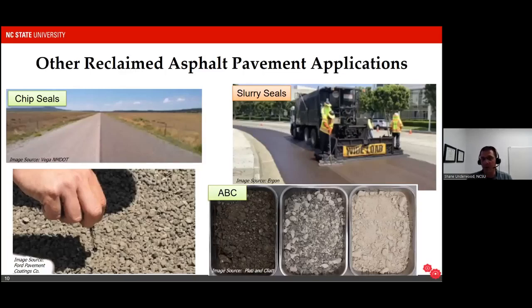But it does create problems because the chip seal tends to only use the coarse fraction of the RAP. But as you can see in the aggregate base, there's quite a bit of fine material left over. So when agencies use RAP in chip seals, there can be some stockpile management issues that have to be dealt with and overcome. One way that some agencies have found to deal with that is to incorporate the RAP-based materials into slurry seals or microsurfaces, which do use the fine fraction. And so it's kind of a balance. You can use the coarse fraction for chip seals and the fine fractions for the microsurfaces and slurry seals that you might use. There are a lot of applications of RAP in asphalt, not just in using them in the asphalt concrete itself. So we have a lot of different ways that RAP can get incorporated.